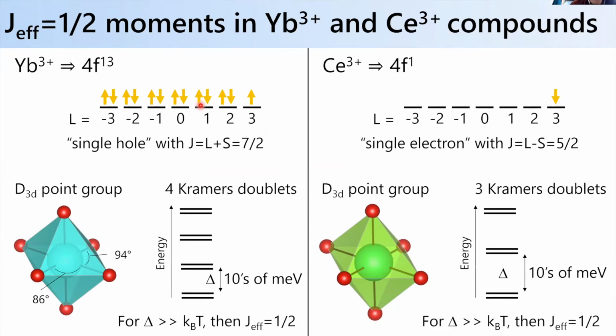You can use Hund's rules, and you can determine that this is going to give me a single hole in the shell with a J of 7/2, okay? And then the crystal field, or the interaction of this shell with the ligand field, or the oxygen ions in the system, will then lift this degeneracy of the 7/2 manifold. In particular, if you put it in a D3D point group, which is a trigonally distorted oxygen octahedra, then you break this J 7/2 manifold into 4 Kramers doublets.